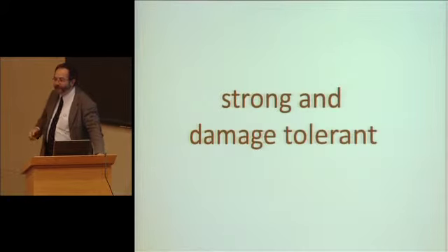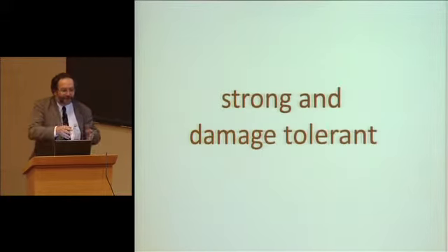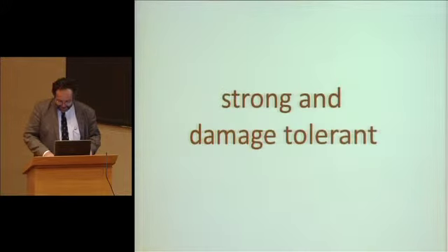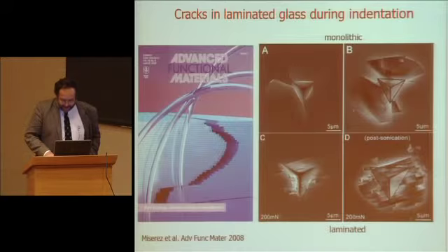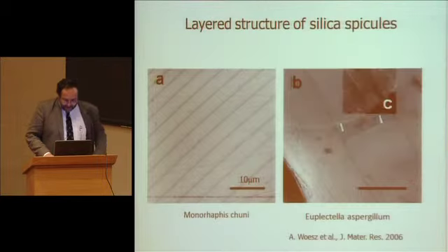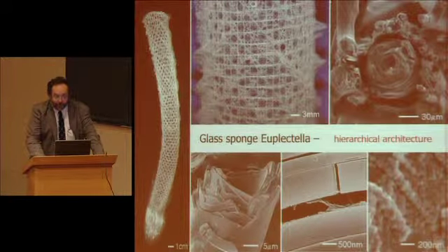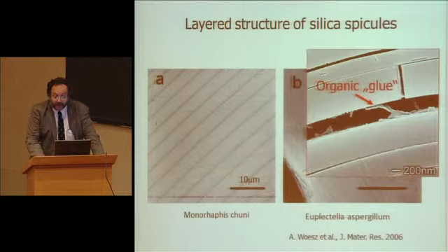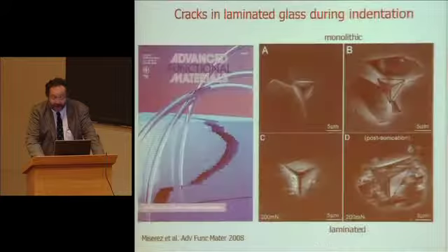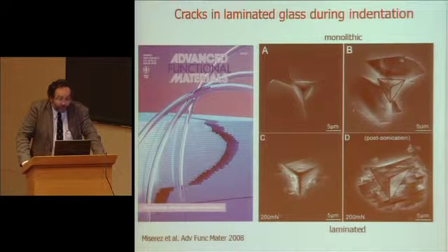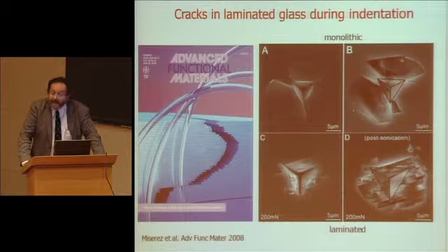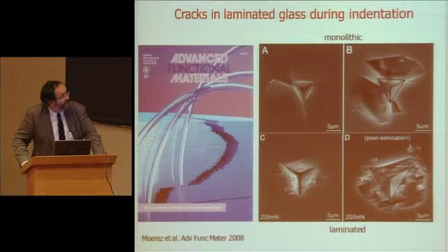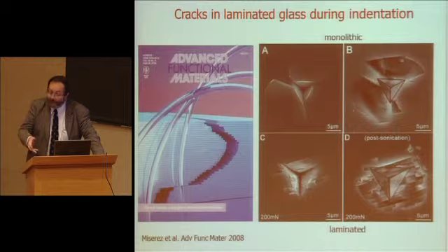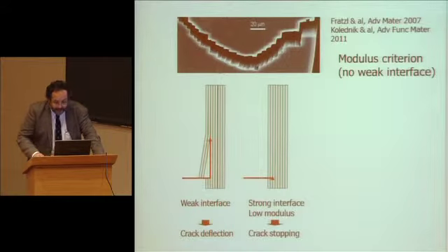So let's look at my favorite contradiction. We want something that's strong and damage tolerant. I know, it sounds like I'm a bit obsessed with that, but this is one thing that we saw. The first solution we had a look at was this sponge structure, where we had a multi-layer solution. Here the organic glue between the various layers. And this is another multi-layer structure. It's the kind of thing you can do either on the solid material with an indentation, and then you have the lamella material underneath, and you can see that you have something that's absorbed much more energy in order to do the indentation.